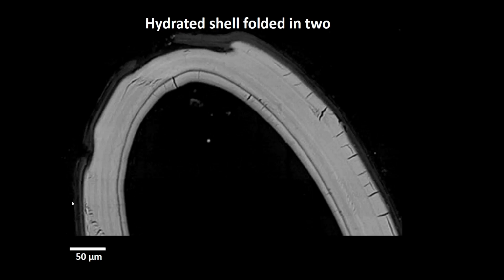And this is the image that we see here. That's an SEM image of a shell that is hydrated and folded in two. And we see that it didn't fracture, which is what you'd expect. And we can soak bone in water for as long as we like, and we'll never be able to do this with a piece of bone. We can't do that with calcium carbonate from a piece of seashell or a sea urchin spine. And of course, water is part of these materials and contributes to mechanical properties. But we don't have this response to hydration, and we'll never be able to get mollusk shells and bones and teeth and so on to fold to that extent just by getting them to absorb water.